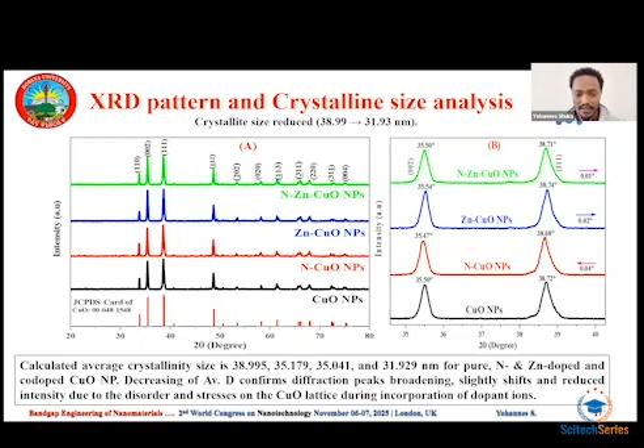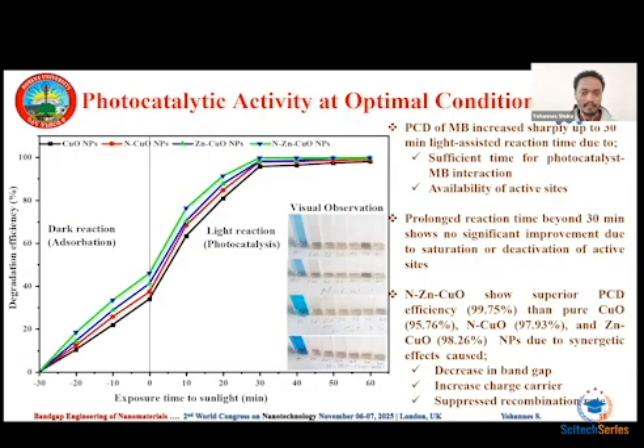This decrease of average particle size, the slight broadening and shift of the diffraction peak from the original sites, and the reduced intensity are due to the disorder and stress on the copper oxide nanoparticles. So here is the application part, the application of this material for photocatalytic degradation activity, which confirms the alteration of the optical property by using bandgap engineering with suitable dopants, that is nitrogen and zinc.